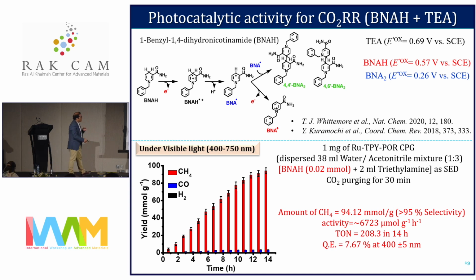Earlier, in presence of the triethylamine, we got CO, but when you use the BNAH, this produces CH4 with a significant amount, 94.12 millimole per gram with 95% selectivity. And the rate is 6.7 millimole per gram, and the turnover number is quite significant, 208.3 in 14 hours, and quantum yield is 7.6%.